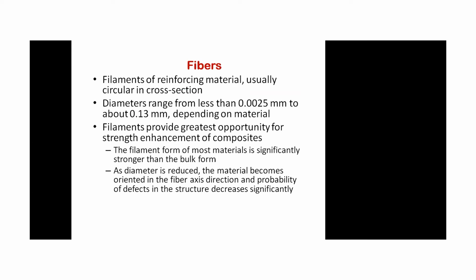Usually they have a circular cross section, with diameter ranging from 2.5 micron to 0.13 mm depending on the material. And as I've told you, the filament of any material is significantly stronger than its bulk form. As you reduce the diameter of any filament fiber, the material becomes oriented in the fiber direction, and the probability of defects decreases significantly. Larger the diameter of the fiber, more can be the defects. But when the diameter is reduced, the defects will be reduced. So the thinner the diameter of the fiber, the more the strengthening.